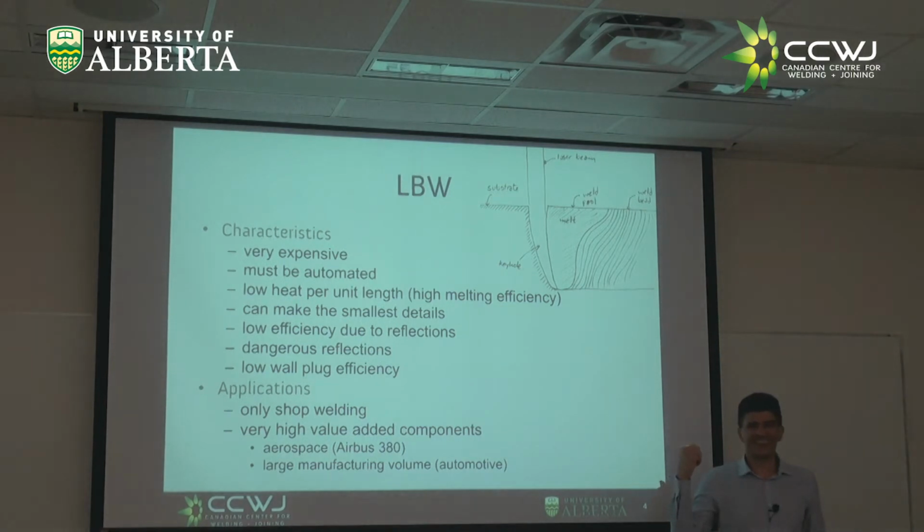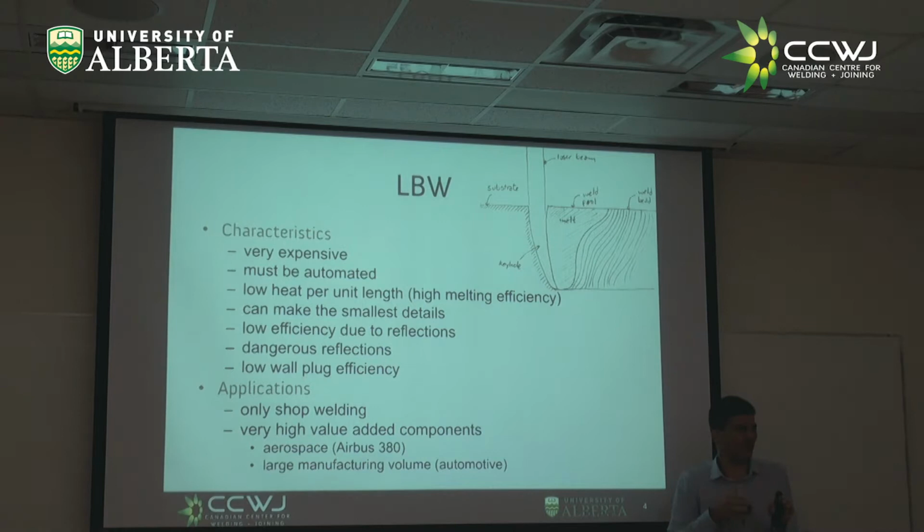Isn't that crazy? Like a suicidal laser is a real problem. So if you go to industry, you're going to see that laser setups are never straight. And you say, well, why don't you make it straight? No, they don't want it straight, because if it is straight, the light can go and come back through the same hole, and with very bad consequences.